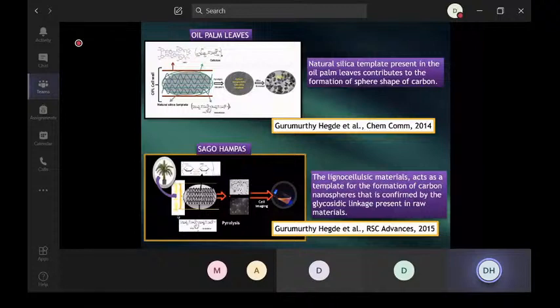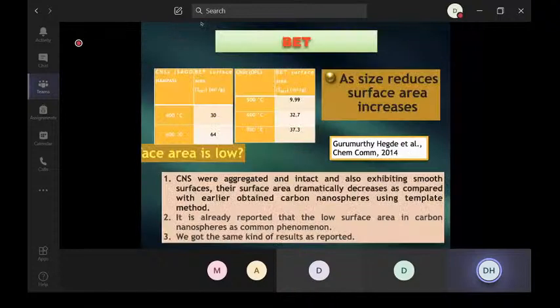So then we did surface area studies, and we got surface areas of 30 and 64, and for sago hampas and oil palm we got like 9, 32, 37. If you see any nanoparticle person looking at this surface area, they will laugh at your results, because people are talking about 1,000, 2,000 square meters per gram for the surface area, and ours is extremely low. Then we again got disappointed, because we did all our experiments and all the characterization, and we found the reason why they are nanospheres, but surface area is a really disappointing result for us.